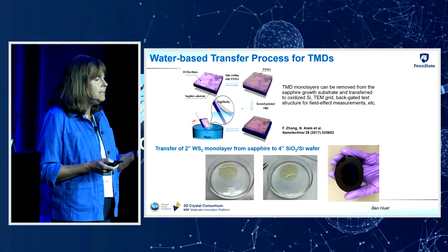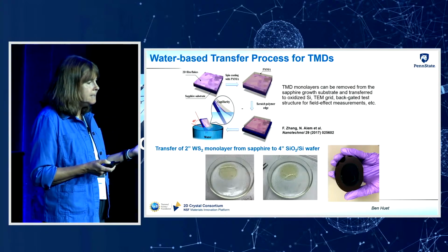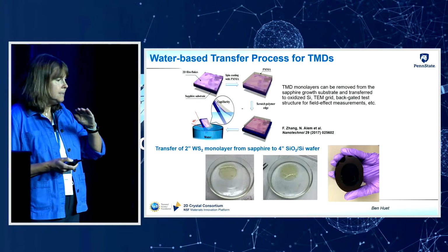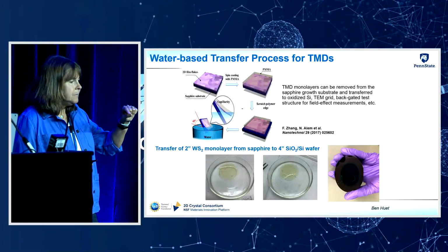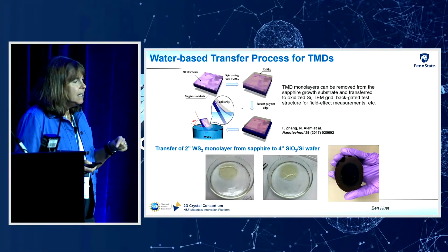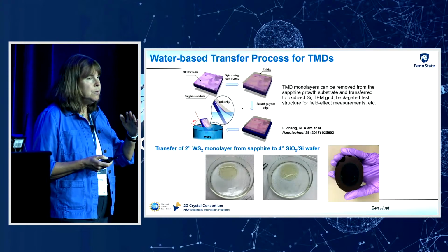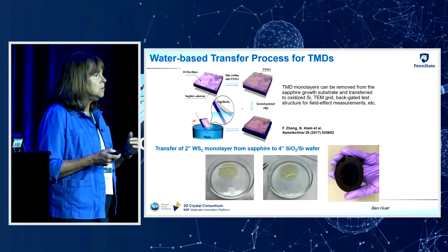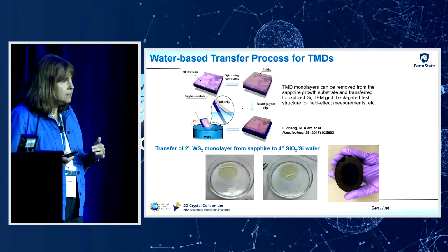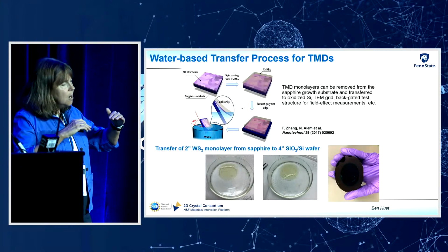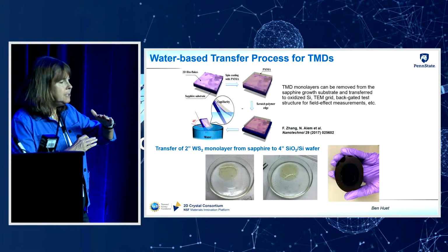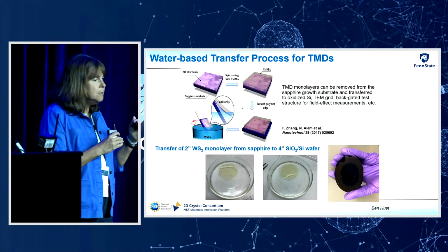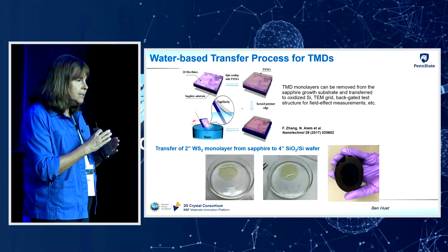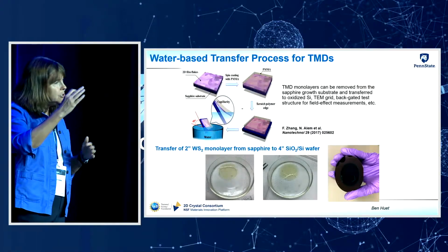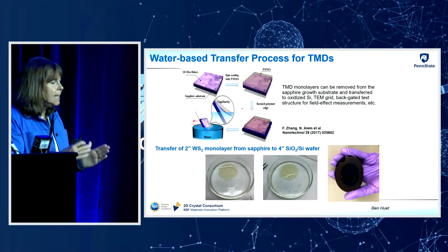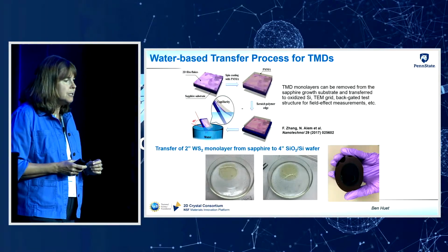We do this using a water-based transfer process. So we coat the sample with PMMA and then scratch around the edges and immerse the sample into either DI water, or maybe a dilute sodium hydroxide solution. And when the water gets underneath the TMD film at the interface between the film and the substrate, it helps to lift the film off of the substrate because, again, it's just attached by weak van der Waals forces.